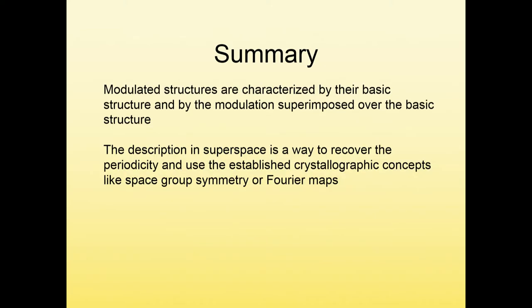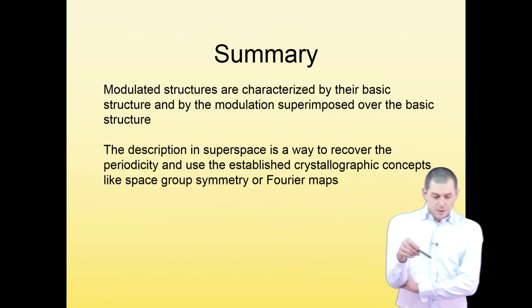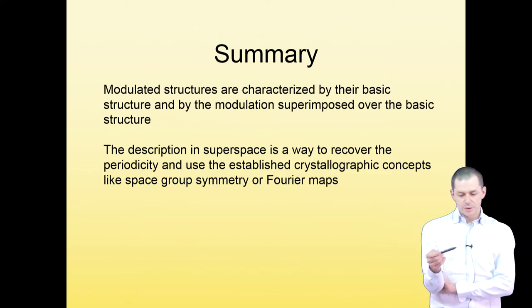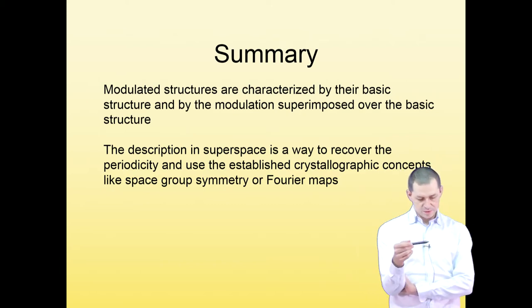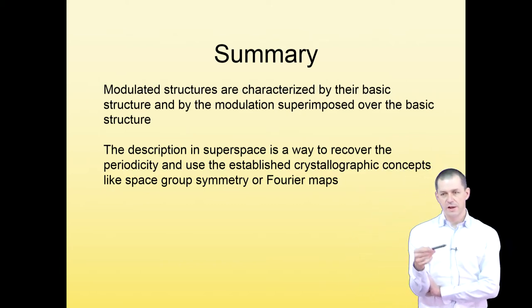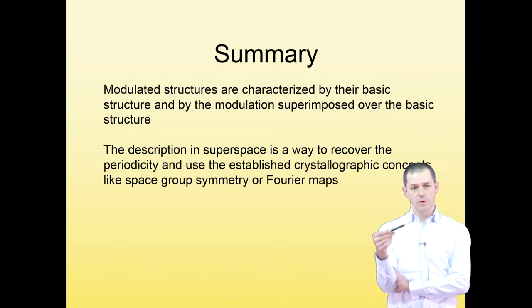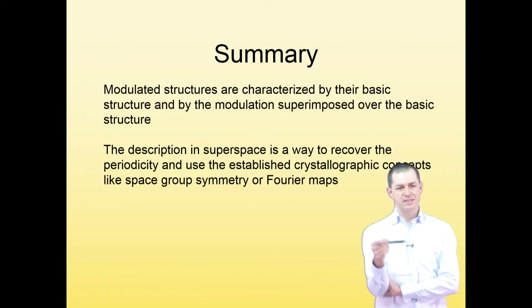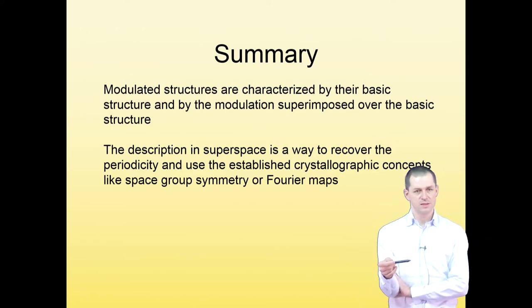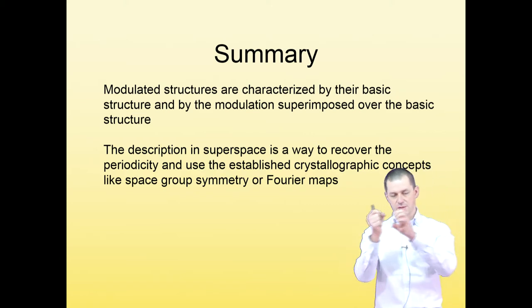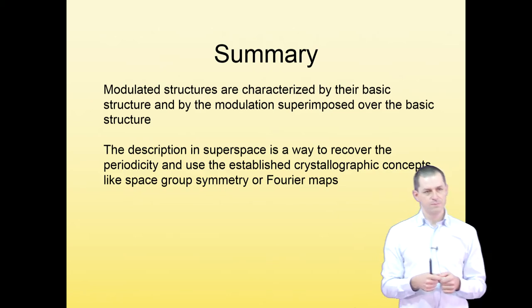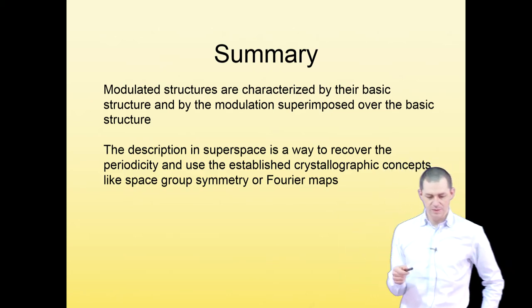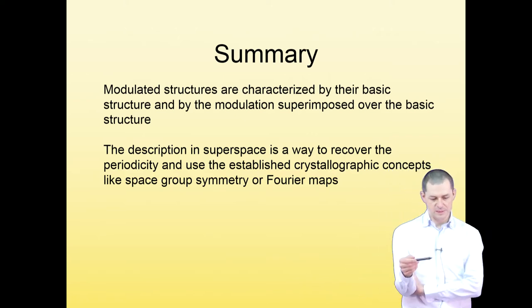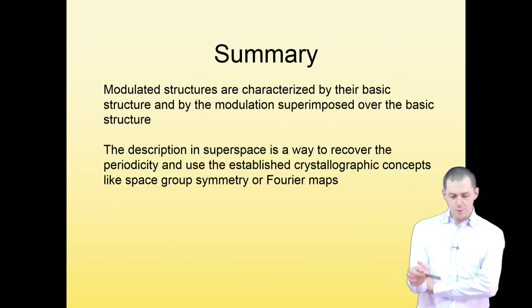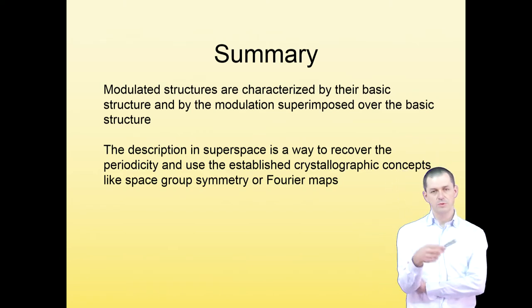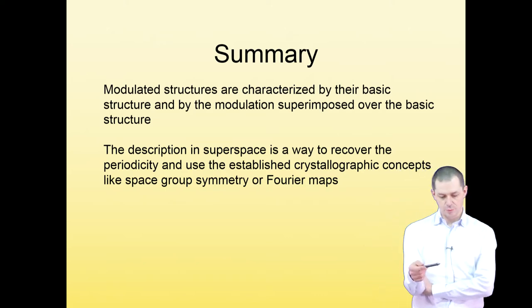So to summarize, modulated structures are characterized by their basic structure and by the modulation which is superimposed over the basic structure. In diffraction space, they are characterized by the presence of additional, usually weak, not always weak, but usually weak or weaker satellite reflections. And this is the way to recognize them. So if you look at the diffraction pattern, there is a principal strong periodic lattice and some additional peaks which are weak and which do not fit the basic lattice. And the description in superspace is used to recover the periodicity and use established crystallographic tools like the space group symmetry or Fourier maps.